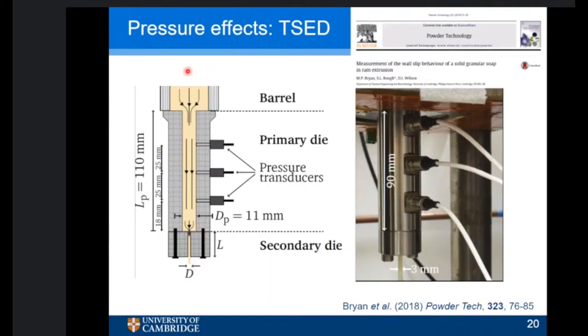So we make the material flow from the top through one change in size and through a second change in size. And rather than measure the extrusion pressure, we measure the normal stress acting against the wall with pressure transducers, and that's what these things are here. These are pressure transducers, and we measure the pressure at the different points, because here we effectively have a pipe flow moving along that system, and by the gradient in the normal stress, we can work out the wall shear stress. So it's a relatively simple concept. It's just a bit complicated to make. Okay, and the other thing we can do is we can change the length of the secondary die. So if we make this shorter, it means we don't need such a big pressure drop in order to extrude it, which means the pressure in the primary die will be smaller.